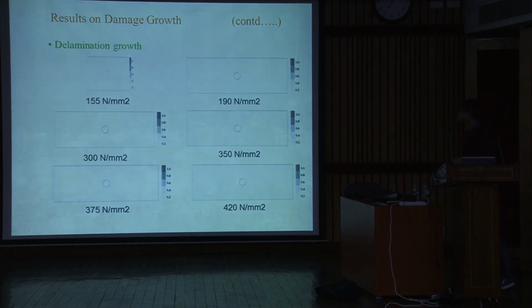Again, in this case also you see a delamination. So what is happening? You have the plies like this, plus 45, minus 45, and my load is applied like this. So why do you see delamination? When you are applying the load, these plies will try to orient along the loading direction. So that will weaken the interface.